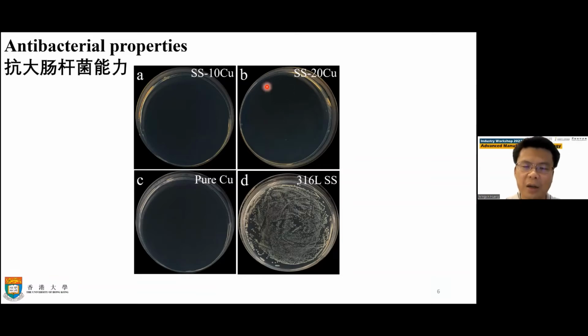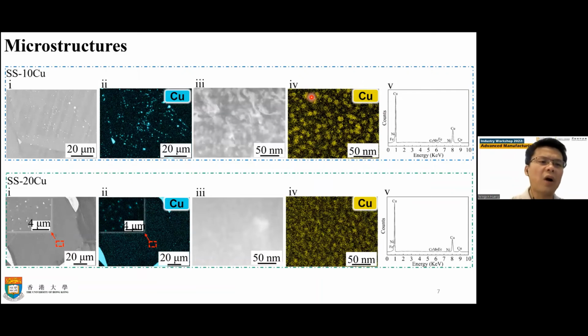So for our materials with 10% or 20% copper, you also have excellent antibacterial properties. So in short, this stainless steel with 20% copper has the best antiviral and also antibacterial properties. Okay. The reason why our stainless steel can have this antibacterial property: if you look at the microstructure with 10% copper, you will see that all these white dots are copper precipitates. Okay. Now this color here represents the copper.